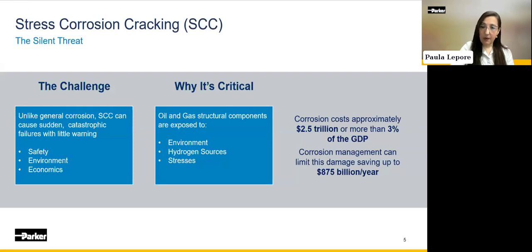Why should we monitor closely? Oil and gas structures and components are exposed to H2S, CO2, chlorides, caustics, overall sour environments, cathodic protection, welding, high pressures, temperature gradients, and residual stresses caused by welding and fabrication, for example. But overall, corrosion costs a lot to our industry. In a recent study published by AMPP for NACE, we know that these numbers go as high as 2.5 trillion per year. However, we'll show you here that there are some simple ways to monitor and manage these types of phenomena, saving us up to $875 billion per year.